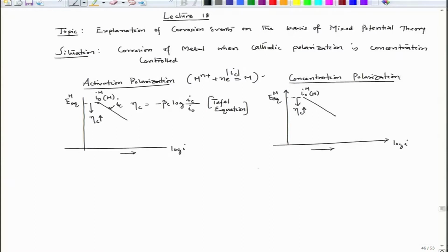Now, as we go from a low current density to a higher current density, I am talking about I C, my governing equation initially will of course be eta C equal to minus beta C log of I C by I 0. Since I am putting a minus sign, beta C is taken as a mod value. That means only the slope value I am considering, not taking the negative sign. If I put a negative sign here, that suggests that beta C is positive.